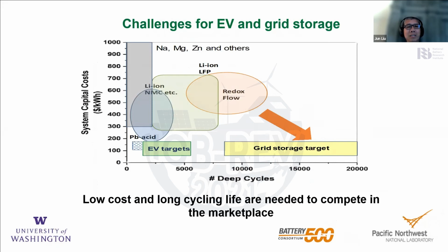Lithium-ion batteries with NMC or NCA system can get close to less than $200 per kilowatt hour, and roughly less than 5,000 cycles. We need to reduce the cost to much less than $100 per kilowatt hour. But for energy storage, the main challenge is to take the same type of battery chemistry and make it last much longer, more than 10,000 cycles. Then we get a few cents per kilowatt hour.